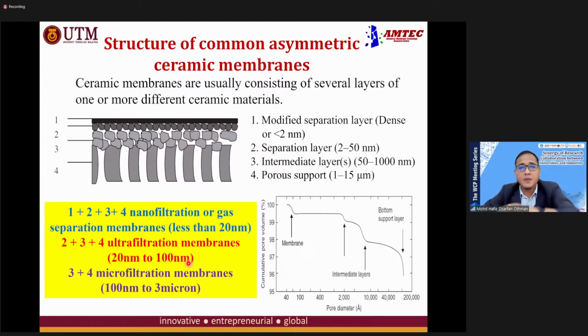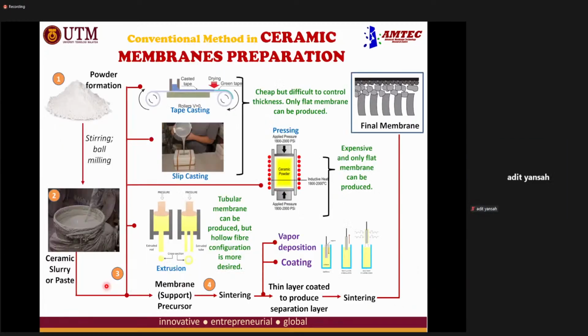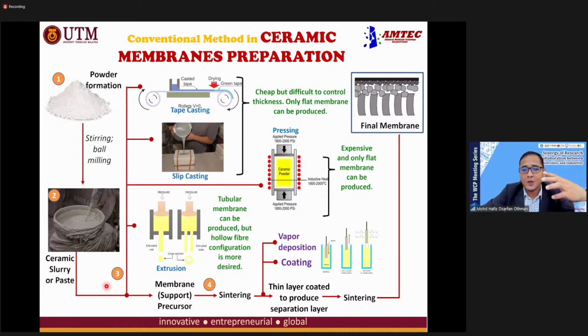Okay. So the conventional way to prepare the ceramic membrane is shown in this diagram. We mix the powder together with the solvent in order to produce the ceramic slurry and paste by using a stirring or ball milling method. After that, we cast them, or form them into a precursor either as a flat sheet or tubular, using tape casting, slip casting, pressing, or extrusion. After that, we get the support precursor, and we have to do some sintering. So this is only to produce the support.